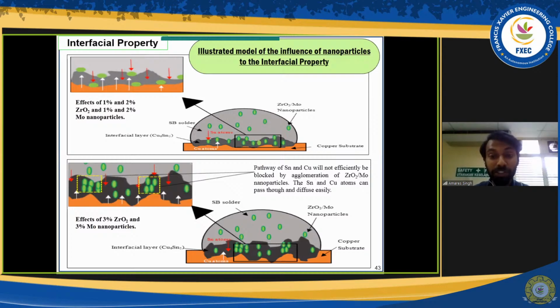So even though there is production of IMC layer, they are not as thick as what is being found in the 3% zirconia and 3% molybdenum. This is simply because 3% of zirconia and 3% of molybdenum has a high weight percentage. So the tendency for agglomeration to happen there is much more compared to the 1 and 2%. Even more so for the molybdenum, because molybdenum is a larger size particle. So looking at that, I've seen the presence of agglomeration at the interfacial layer. Although there is a blocking of diffusion by the non-agglomerated particles, in some places that were agglomerated, the blocking of diffusion is reduced.